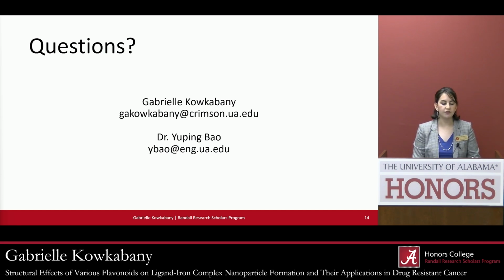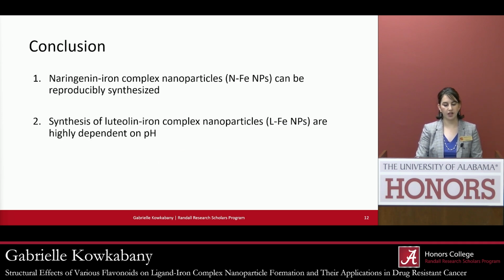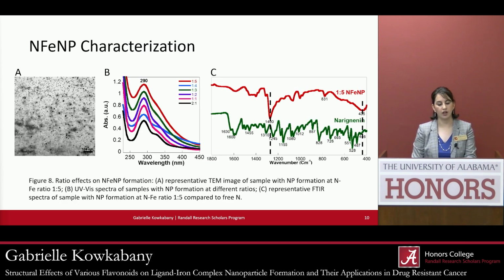And then generally, if a nanoparticle is around the size of 20 nanometers, that's ideal when you're thinking about the incorporation of these nanoparticles in, for example, a murine model or in human studies, because those won't actually get trapped in organs like the liver or lungs, and they have the highest bioavailability. But really, there's not a size that we're necessarily aiming for. And then to go further than that, if you look back in this image of the TEM, you can see that there's a difference in the uniformity of the nanoparticles that are in this image. They're arranged between 5 nanometers to 20 nanometers. And so we're really looking for something that's more consistent than that. And so we can play around with the reaction kinetics and other factors to try to increase uniformity, for example, by doing this reaction at a lower temperature.